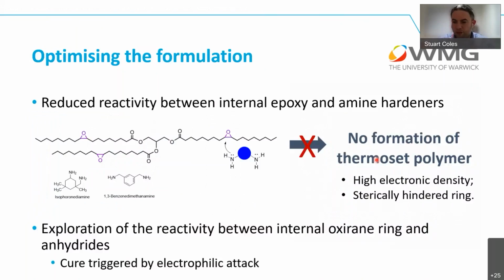One of the other reasons that we found this problematic is that the amine hardener in our system wasn't particularly good. It didn't really react with these internal epoxy rings. If you had an epoxy ring at the terminal there, it would work really well. But here, because of the steric hindrance of these large bulky amine hardeners, we weren't getting a reaction in here. And there are a couple of examples of what these amine hardeners typically are like within epoxy resin systems.